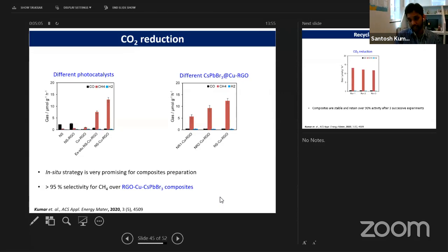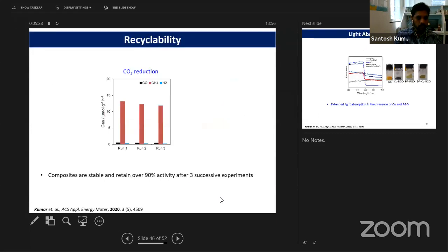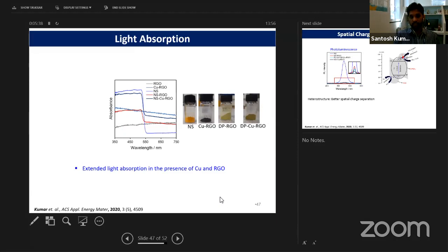It's much higher, even much higher than with the nanorod, because graphene is two-dimensional, and in the case of a two-dimensional perovskite structure, both are two-dimensional, so you have a face-to-face interface. So the contact along the interface is much higher than in the case of the nanorod, as I discussed earlier. And then more interestingly, you see the reproducibility is much higher than pure. Pure was not stable, but the composite is much more stable and steadily reproducing.